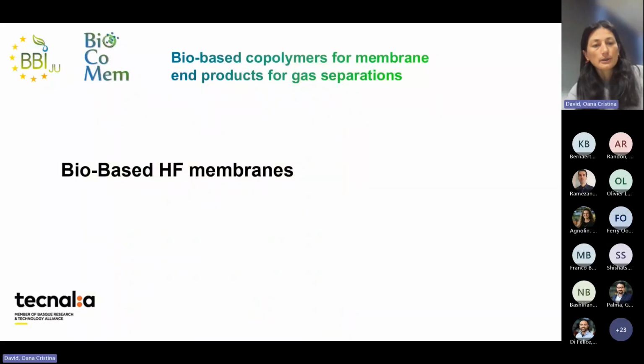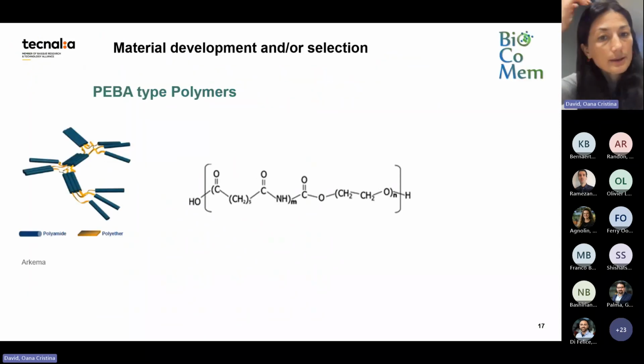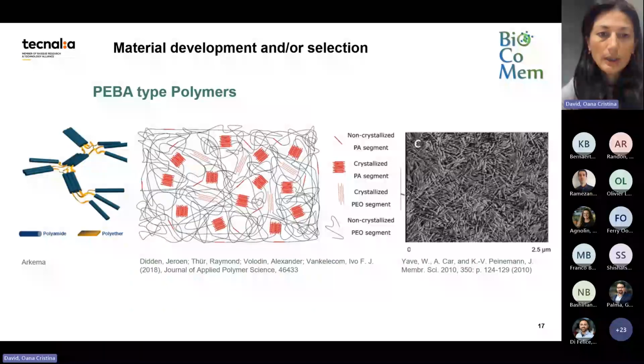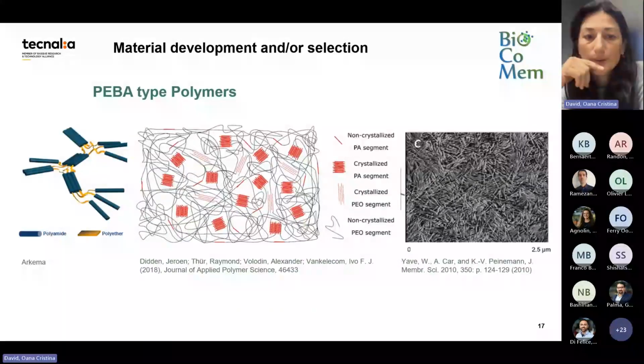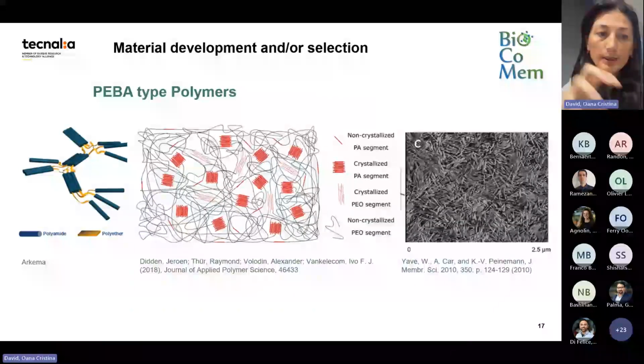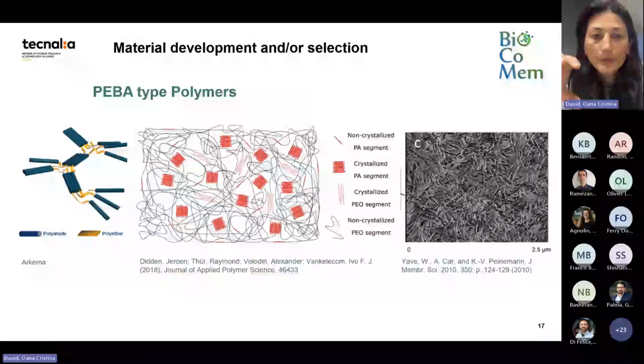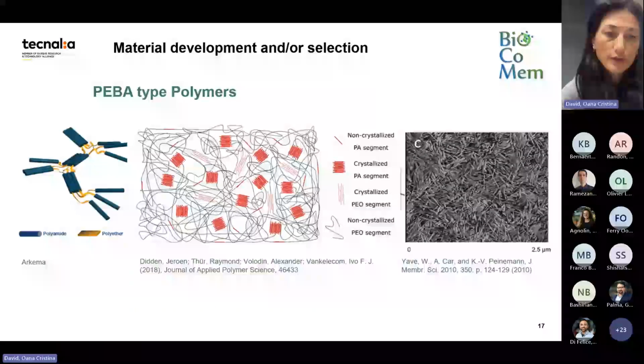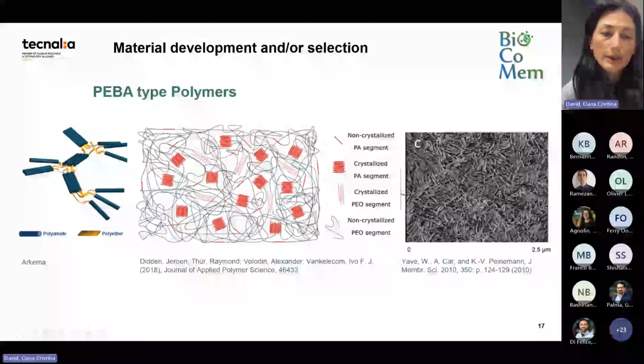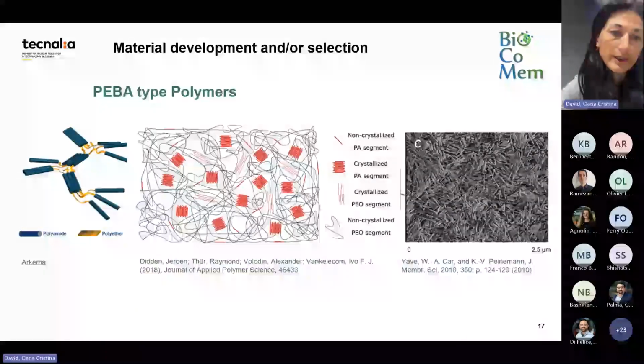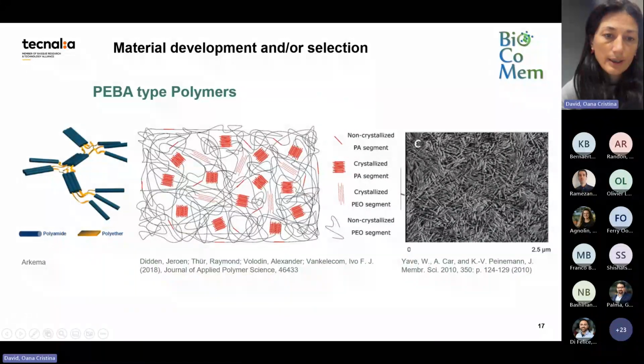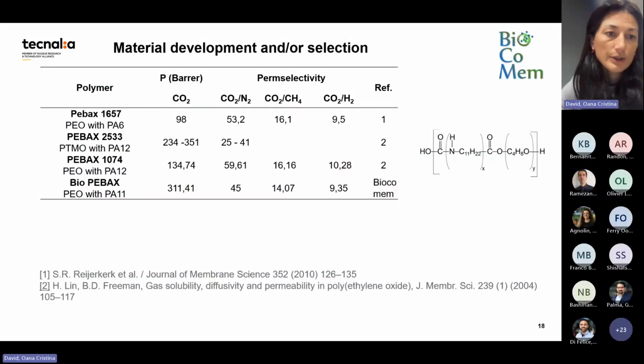And now I will start showing some results we have in the Biocomem project. So I start, why we use PEBA type polymers was very nicely shown before, so I will not show it again. But in this kind of graphical representation, you can see that these block copolymers can form domains of polyethylene oxide flexible network where carbon dioxide permeation is preferred, and then we have the polyamide part that is making a reinforcement of the polyethylene oxide flexible network. So this is the benchmark.